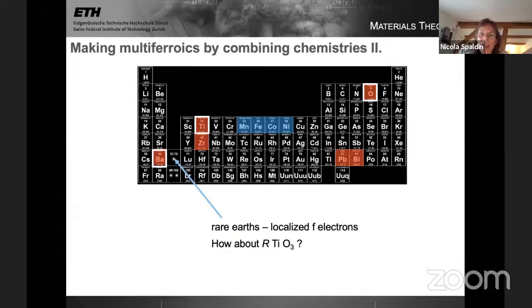But I'll just quickly show you the kind of opposite example, again in the perovskite structure, because this is relevant to the question that was asked earlier. In the periodic table we looked at earlier, we didn't mention these rare earths, which have very localized f electrons. In bismuth ferrite, we put the magnetism on the transition metal and brought the ferroelectricity in through the bismuth counter ion. What about leaving the transition metal to be ferroelectric and introducing the magnetism on the rare earth?